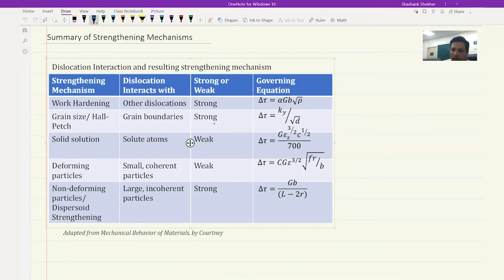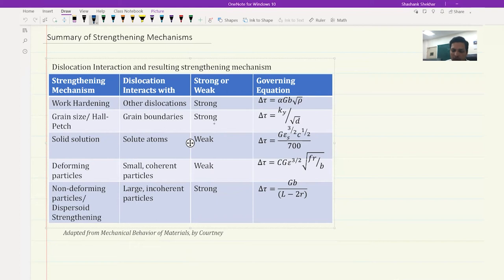The governing equation for solid solution strengthening uses G as the modulus, epsilon as the strain, and c as a concentration factor. Then you have the precipitates, where you can have small precipitates or large precipitates. Small precipitates are coherent, where cutting takes place. For the large precipitates, it is the Orowan loop that forms around them - this also governs dispersoids. For the small coherent particles, the strengthening effect is weak, but for the large incoherent particles, the strengthening effect is strong. These are the governing equations in the summary table.